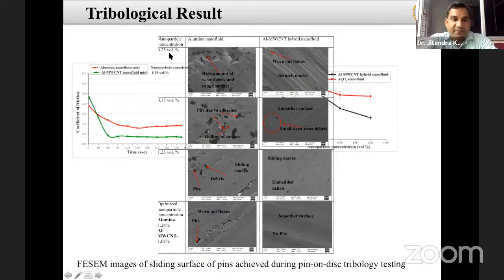So for 1.25 volume percentage particle, we can see that both alumina and this hybrid give a better surface than the single particle. And for this optimum, you can see that a smoother surface is obtained, with no pit formation on the pin surface. So this shows that the optimum results we have obtained are confirmed as correct. So these are the few analyses done in this area.